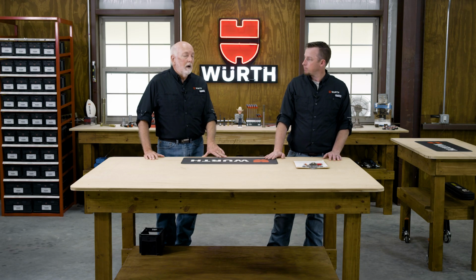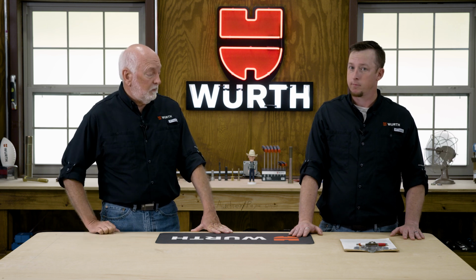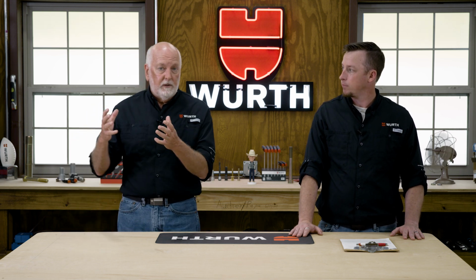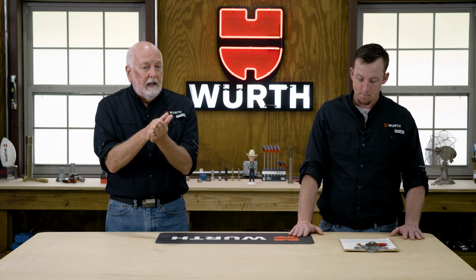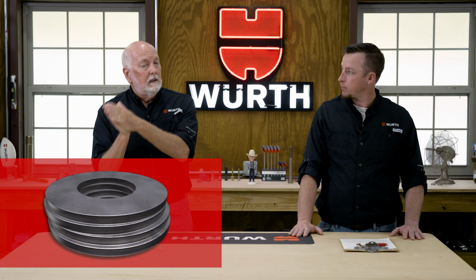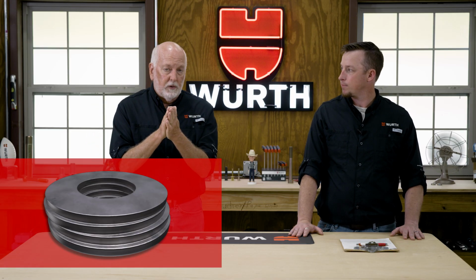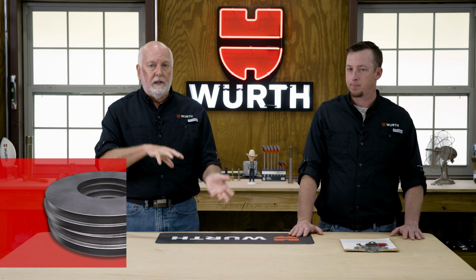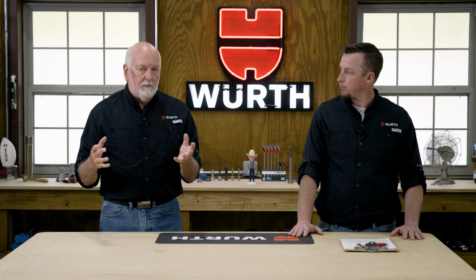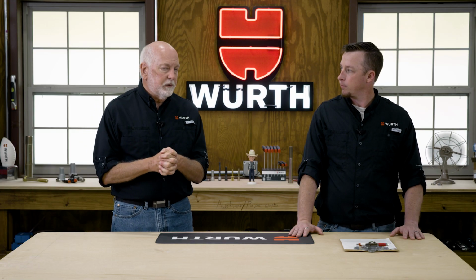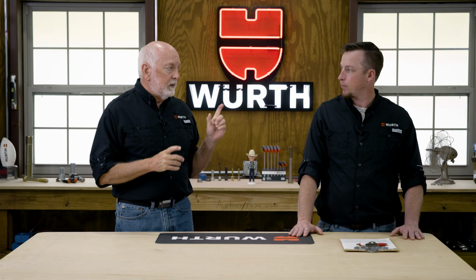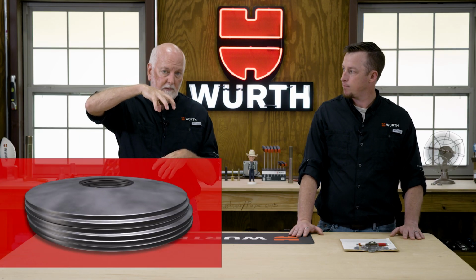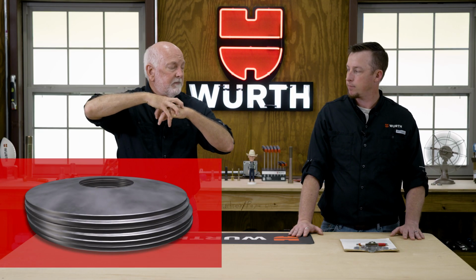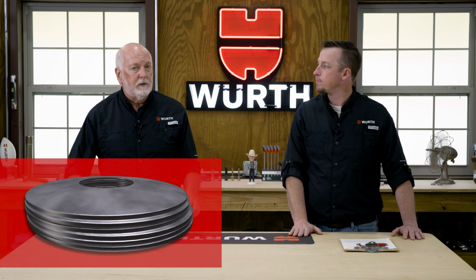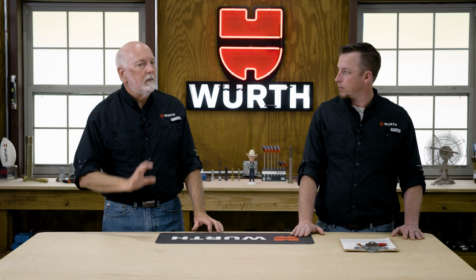Sure. Big concern there. The other thing is nesting of flat washers. Same situation. You've got a stack of flat washers, you dip it, you spin it, and if they end up staying stacked in the cure oven, then they will actually cure together. So the applicators will do things like drop them on the conveyor belt to try to break them apart, but it is a concern on flat washers. Conical washers are a particular concern because of the conical shape, they nest together and it's very difficult to get those apart. So we typically will suggest other means of fastener finishes for those types of items.